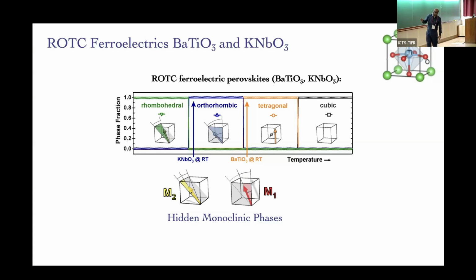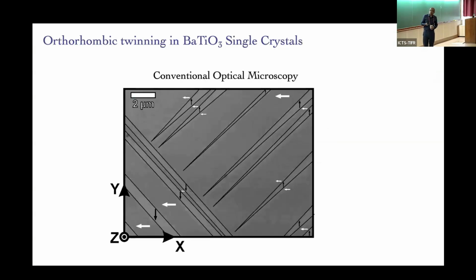Now it turns out it may pop neither along this direction nor the face diagonal, but somewhere in between, and that would be monoclinic 1. Or neither along the face diagonal nor the body diagonal, but somewhere in between, and that would be monoclinic 2. These are not stable phases, by the way. You won't see them in the phase diagram. In single crystals, you shouldn't see them at all. But you'd be wrong to not expect them because I'll show you that they're there in single crystals too.